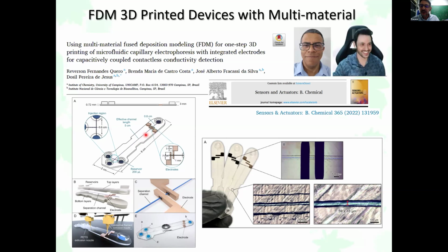You have some options in the market actually to prepare these conductive electrodes. And if you see here, this is the design. So the electrodes are around the central channel. This is really, or I can say this is impossible to prepare using conventional lithography. You have to use many different steps to get this kind of complexity in conventional lithography. And using 3D printing it's pretty easy to design and print the device. One nice thing with this FDM device is that after you finish printing, you can use the device. You don't need new washing steps or curing steps. You can use it directly after printing.